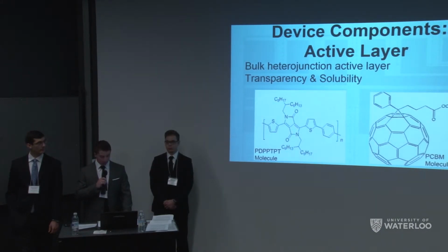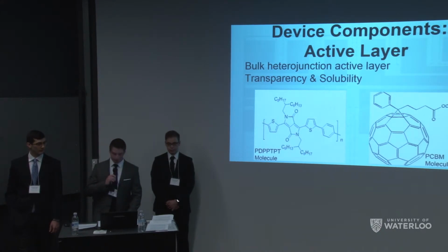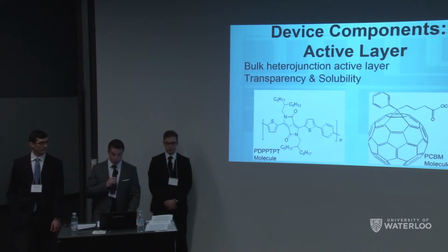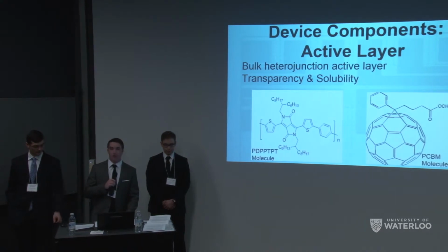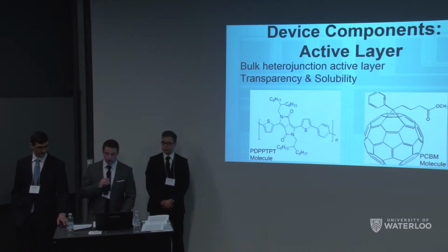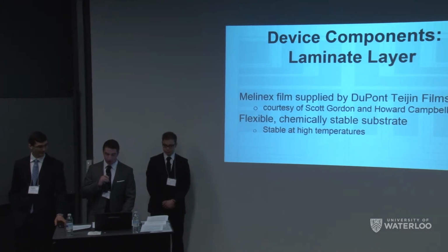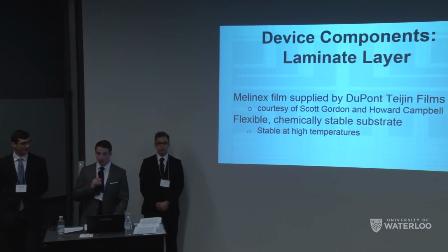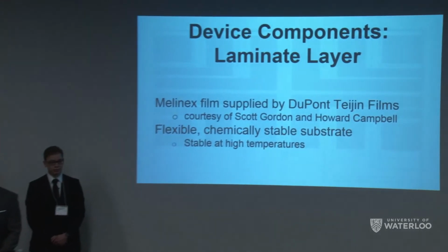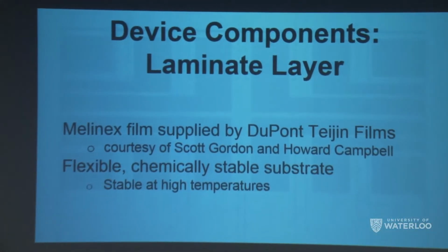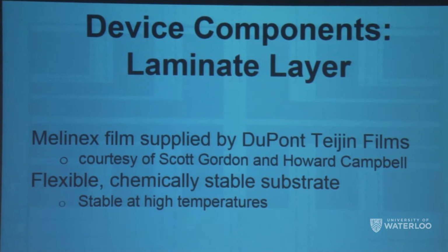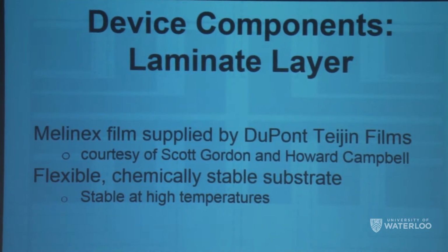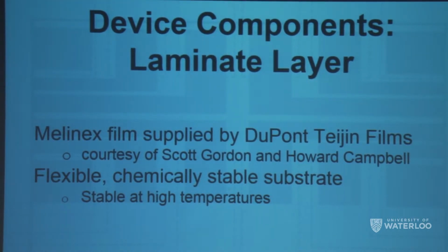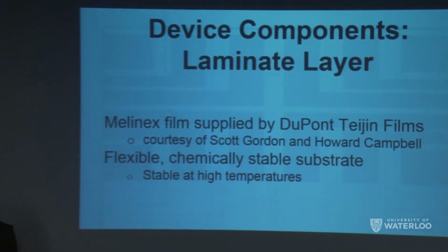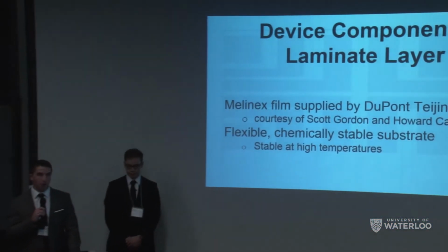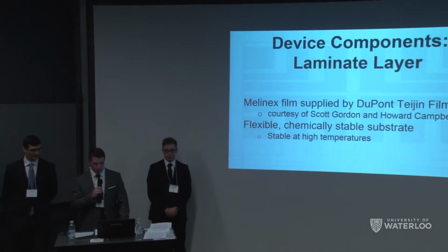The purpose of having both an electron donor and acceptor material is to pull excited electrons away from their corresponding holes, preventing them from recombining and losing the energy they captured from incident light. These two materials were deposited in a solvent and spun onto our glass substrates to have a thickness of about 200 nanometers. Again, to put 200 nanometers into perspective, this is about 200 times thinner than an individual strand of human hair. These two materials were chosen because of their absorbance spectra in the visible range. More or less, these two materials on their own have very little absorbance in the visible spectrum.